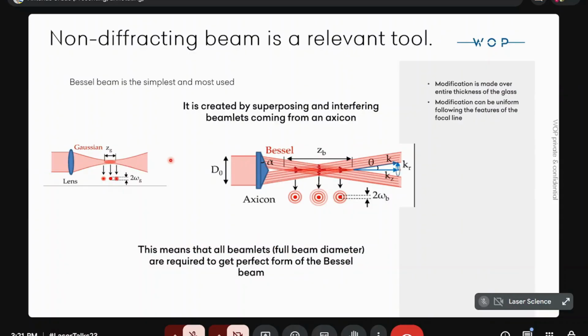So what is important is that this minimum dimension of Bessel beam is 3-4 times less than you can achieve with the same optics in Gaussian beam. Meaning that it is no big deal to get a 1 micron thick needle to modify the glass. So you are much more precise than you would be while having a Gaussian beam focus.